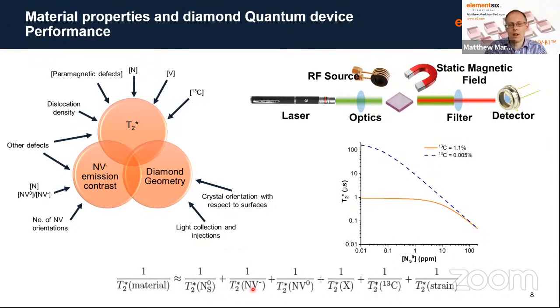Obviously the NVs themselves: the higher the density you go, the more self-interaction you can get. NV0 can also have an effect. You can also get other parasitic defects, which I'm denoting X here, which can have an effect on the spin lifetime. The isotopes too: carbon-13 in natural abundance diamond is 1.1%, and that has a significant impact on the spin lifetime. And one that I'm going to give more detail on later is strain in the material. Strain will shift the ODMR line position and therefore lead to inhomogeneous line broadening. So all these are important factors to consider.